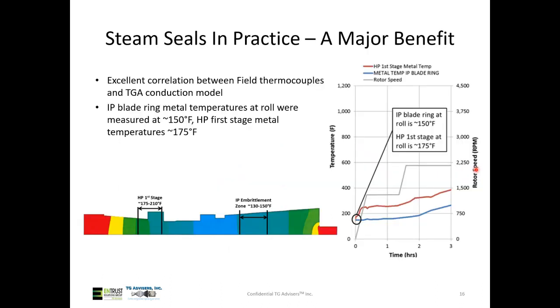Here's an actual unit where we did that modeling, and we had the benefit of looking at an IP blade ring temperature and a first stage metal temperature. So again, these would see lower temperatures because the steam seals are on the back ends. But we saw very good correlation between what our model predicted for heating that we would see propagate through the rotor and what we actually saw in the casing thermocouples, 175 and 150. So again, it's kind of free if you're able to do that.